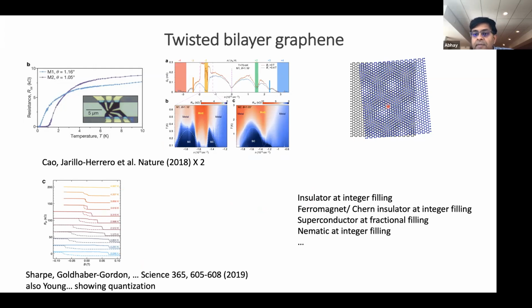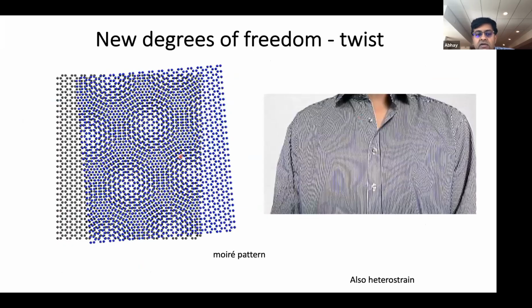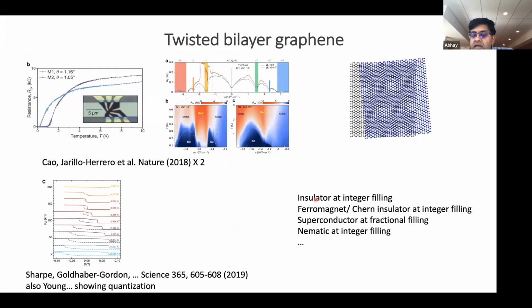that for this system, at integer fillings of this large unit cell, I forgot to mention this, once you introduce this kind of Moiré pattern into the system, the unit cell of your lattice becomes much larger, and the unit cell is now this wavelength. And by applying a small amount of doping, a small amount of electrons per individual unit cell, you can fill up these large unit cells very easily.